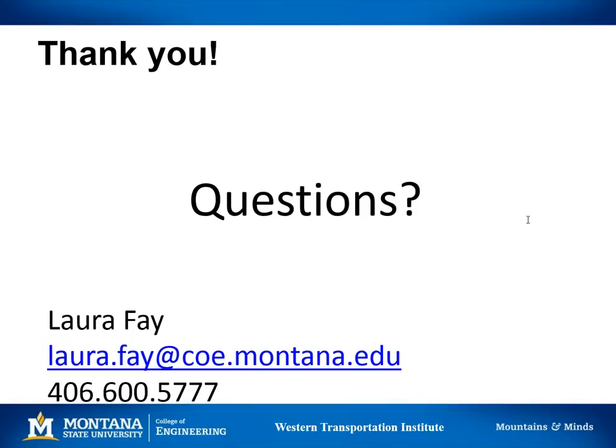It says, Clay asks, what % solution of Ice Slicer did you test? For the ice melting test, it's applied directly as is. So the grains are sieved so that they're uniform and then applied. For the corrosion testing, they're all tested at 3%. So it's uniform across the board. For the eutectic, I'm going to have Ambu. Ambu did the eutectic testing. Is he on the line still? Sure, yeah. Let me go to that slide, actually. Clay just wants to know what concentration the Ice Slicer was tested for the eutectic curve.